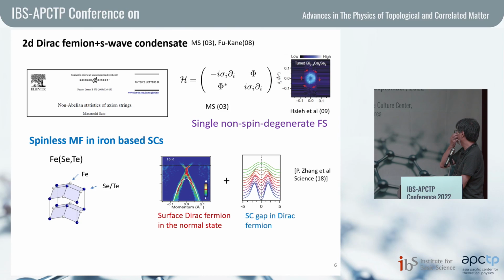Actually, this type of spinless Majorana fermion is realized in the iron-based superconductors. Here I show the crystal structure of the iron-based superconductor, and this is iron, and this is selenium or tellurium. And here I show the ARPES data taken by the group at ISSP, Japan. As you can see, this is the normal state spectrum, and this part comes from the bulk, and this part comes from the surface Dirac fermion. So you can see that there exists a surface Dirac fermion in the normal state.